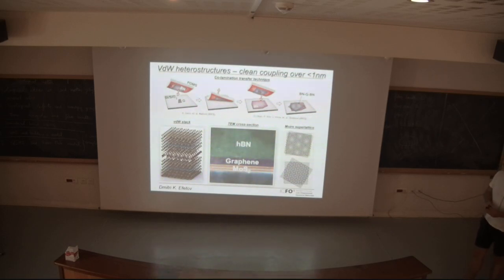Okay, and the surprising thing is, again, as with the discovery of graphene, this is a conceptually simple principle. And I think when we started doing this a couple of years ago, we thought nothing would work. And then again, the surprise was that actually the quality of the heterostructures so obtained is extremely good. So here is, for example, a transmission electron microscope cross-section along basically a device like this, where hBN, graphene, MoS2, another layer of hBN are shown. And as you can see, the interfaces are extremely clean.